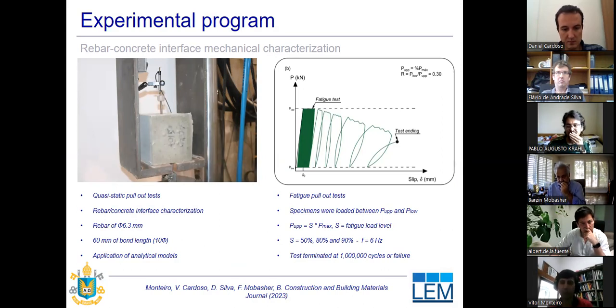For the fatigue pull-out test, we have a similar approach. The test oscillated between the upper loads and the lower loads. The upper load is a fraction of the maximum bond strength recorded from the quasi-static tests. So we could have load levels of 50, 80, and 90% of this bond strength, and it was oscillating between this range of loads until reaching a million cycles or the failure of the specimen.